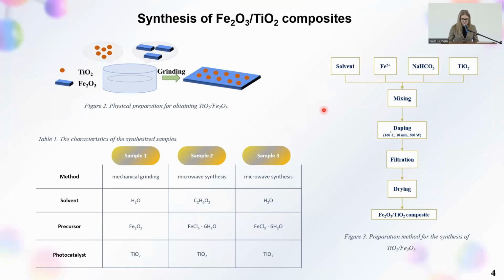The schematic process for synthesis of metal oxide photocatalyst is shown in Figure 3. Titanium dioxide, sodium bicarbonate, and iron ions were dissolved in the solvent, the mixture being stirred well dispersed. The photocatalyst synthesis was carried out in a Discover 2.0 microwave flow reactor at 160 degrees Celsius for 10 minutes. Following the reaction, the mixture was stirred well dispersed, followed by a filtering and drying stage to obtain metal oxide